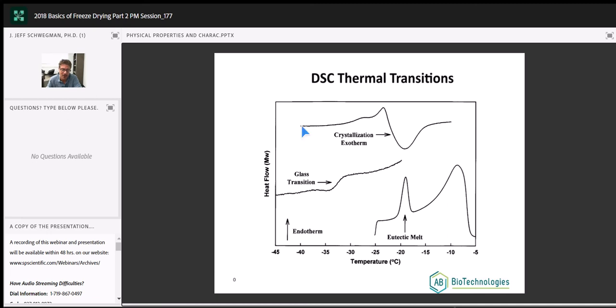Let's look at the metastable glass. How do I know it's metastable? Well, we warm up. If it's a glassy phase, it's going to have a glass transition. We warm up, there's my glass transition right here. We see a little bump, an endotherm, that's called enthalpy recovery, and then boom, we see crystallization by this big exotherm. So what's this telling me? Well, we know we formed a glass, it's metastable, we warm it up. Once we get through the glass transition, as I mentioned earlier, we're no longer a solid, we're a fluid. So the molecules got locked in a random distribution when they froze, metastable glass. As we go through the glass transition, those molecules start to move. As they move, they settle in and crystallize, and that's why we see this big kick out of heat as those samples nucleate and form the eutectic.